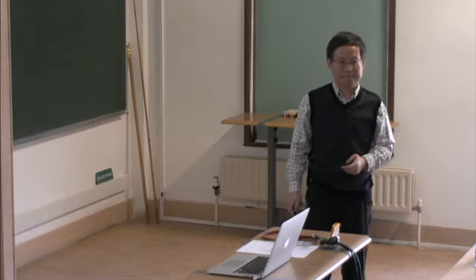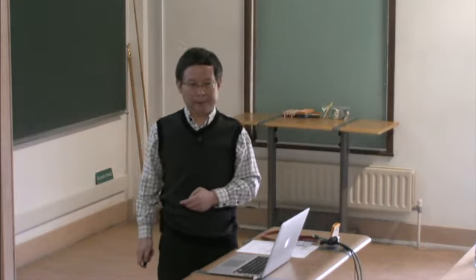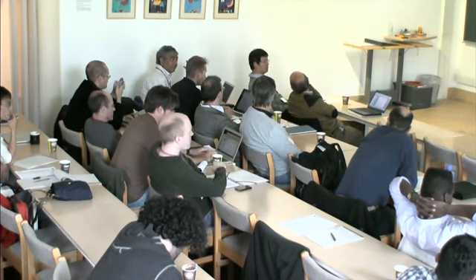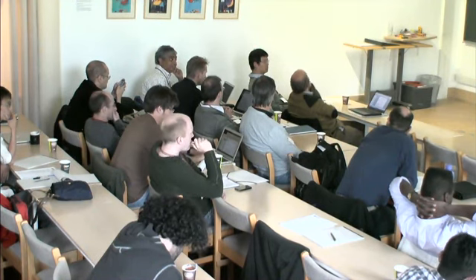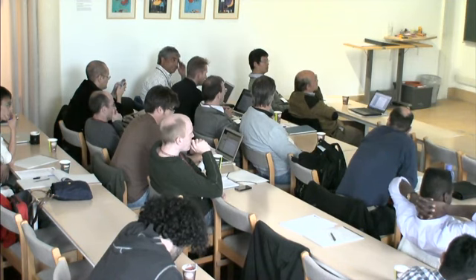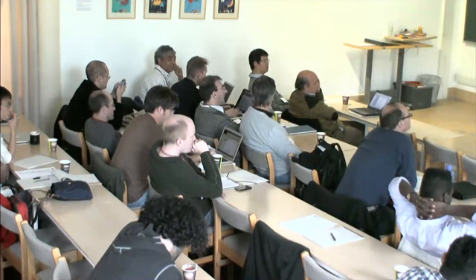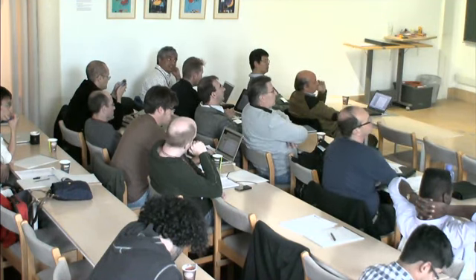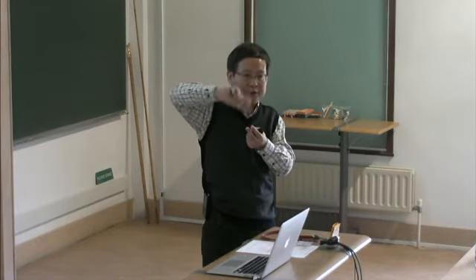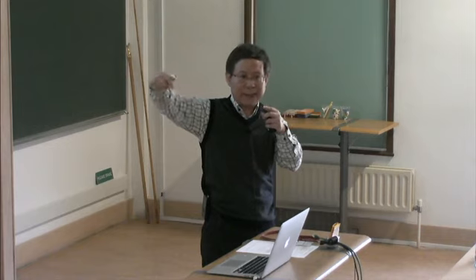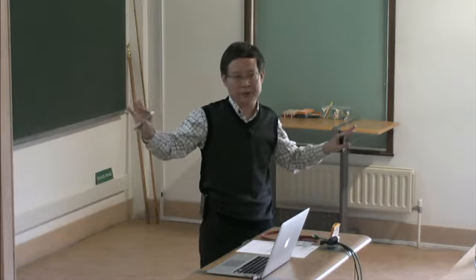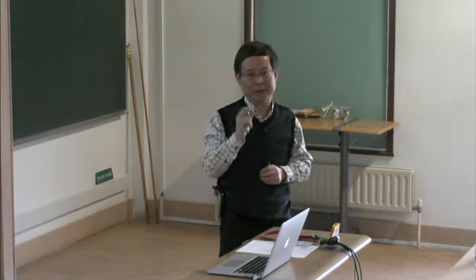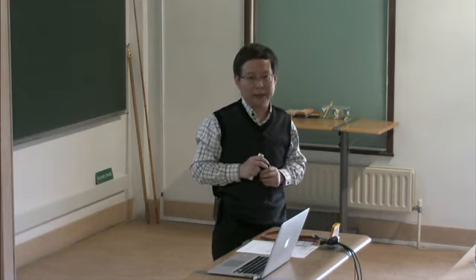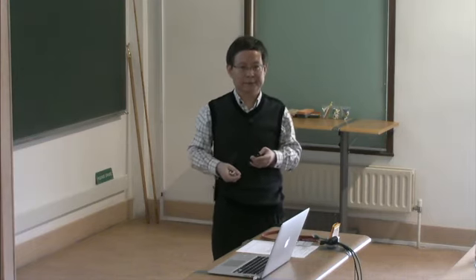So this is basically a quasi-one-dimensional system. If I take an even number of legs and zero doping, I believe that's a spin gap system. Confinement and everything. Sure. So why do you think there's localization in that case? This is very important. When you have a gap, you normally think that the hole hopping will generate something with a gap, so the relation to this quasi-particle is weak. But because this sign is very cheap, it turns out to be a non-perturbative effect. Once you put in one hole, everything is destroyed. So you don't have a perturbative theory working even for the 2-leg ladder. That's the moral of it.